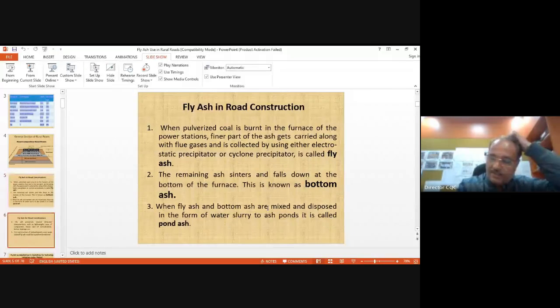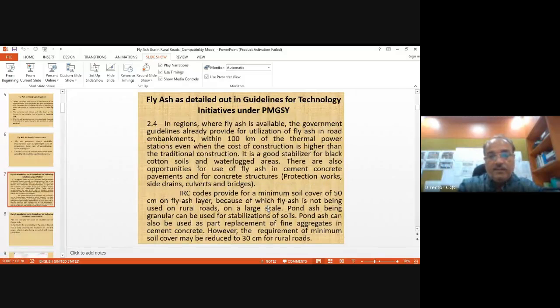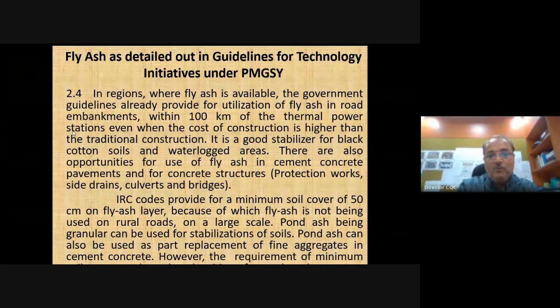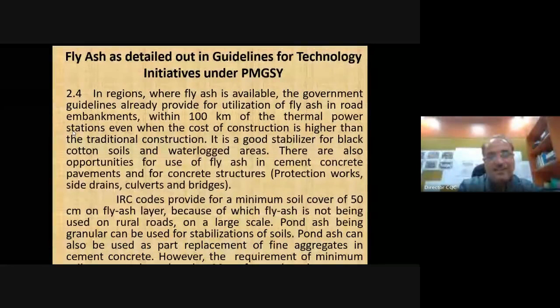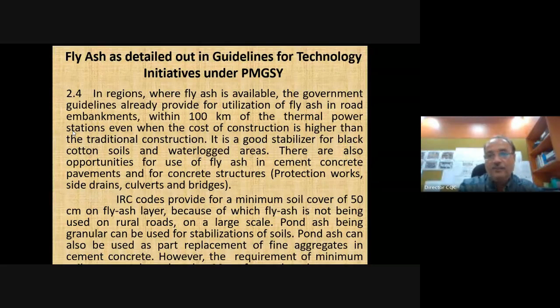in fact, the IRC guidelines provides that there should be a minimum cover of 50 centimeter on fly ash layer. So in our new technology guidelines, as I said in the beginning, our total embankment, including subgrade thickness, is hardly 60 centimeter. And we have to provide a cover of 50 centimeter to fly ash layer. That means only 10 centimeter embankment can be made with fly ash. So just to avoid this, we discussed with a couple of stakeholders, fly ash producers, other scientists working in CRRI and various other agencies, and finally took a decision that out of 60 centimeter, we will be making 30 centimeter embankment with fly ash, and the requirement of all-round cover can be reduced to 30 centimeter only.